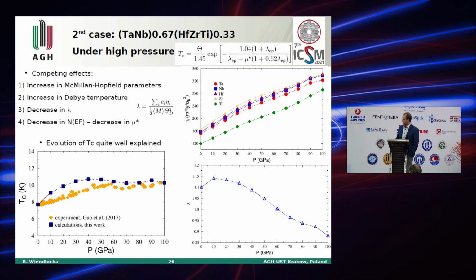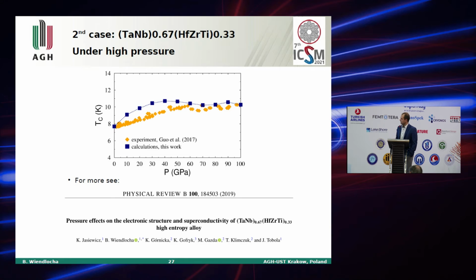However, critical temperature increases because of these competing effects of increase in theta and decrease in lambda, and also because the density of states at the Fermi level decreases, so the Coulomb pseudopotential parameter decreases. So from all these competing effects, we have reproduced this evolution of TC under pressure. So first TC increases and then it stabilizes at the constant level. So again, we see that this is a conventional effect and well described by this effective theory. This work has been published 2 years ago.